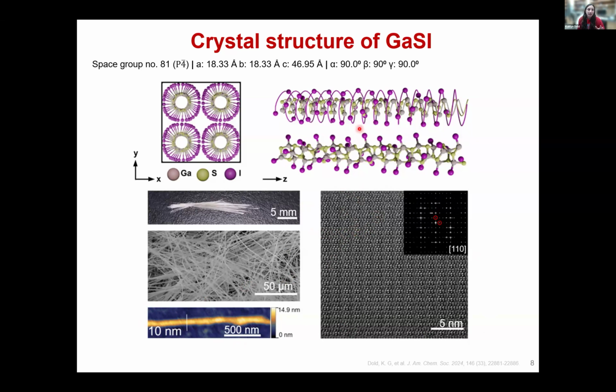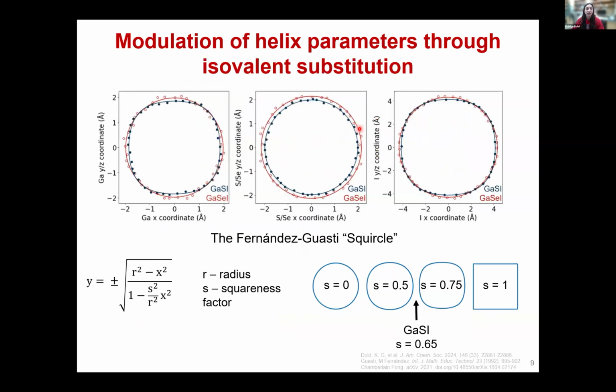So after looking at the structure of this material, I then wanted to look at how the helix parameters changed between gallium selenium iodide and gallium sulfur iodide. I'm just going to talk about the one that was unexpected, and that was when we looked at the cross-section of the helix. Because we're substituting in a slightly smaller element, sulfur for selenium, we expected all of the cross-sections to slightly contract.